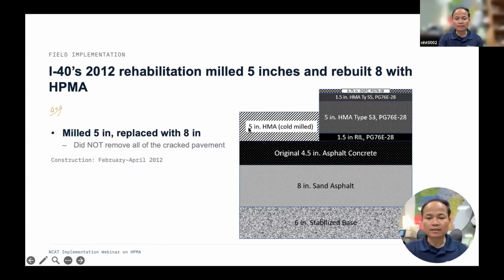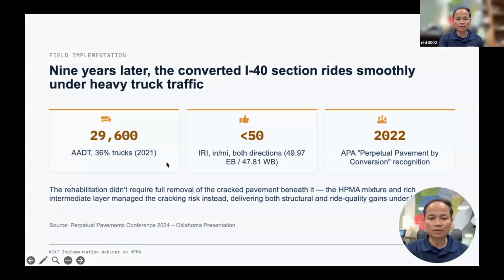They came in and milled 5 inches of HMA, but they did not mill the whole cross section. They left about 4.5 inches of asphalt concrete, the board that has a lot of cracks in it, in place. And then you can see here on top of that, they put in 8 inches of HPMA mixture, very similar to the mix design that was placed at the test track. On top of that, they put an OGFC layer. The construction was done from February to April in 2012.